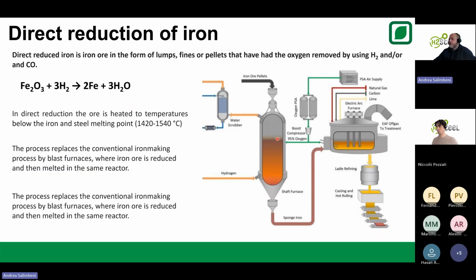At this temperature and with the injection of a reducing agent like hydrogen, but it could also be methane or CO, the iron is reduced to iron metal, producing, in this case with hydrogen, only water vapor as a byproduct, as a gas. In this specific condition, the iron is reduced but not melted. And that is why after being reduced as a metal, it can go to the melting furnace, which is an electric arc or a submerged arc furnace, where the carbon is also added to produce the steel. That is the difference. So direct reduction of iron means decoupling the iron reduction from the iron melting, and it enables reducing the emissions, in particular when hydrogen is used.